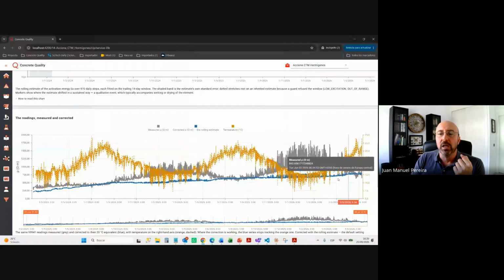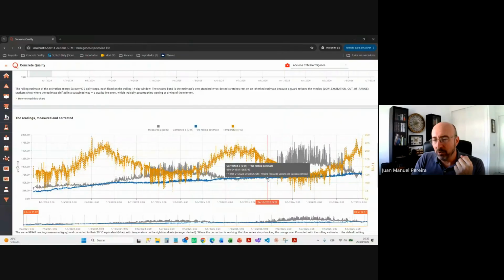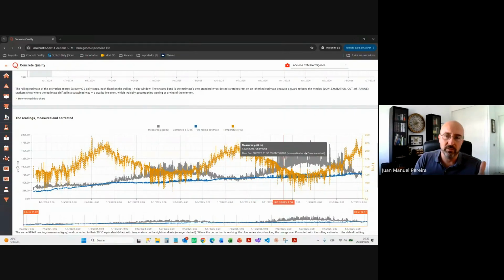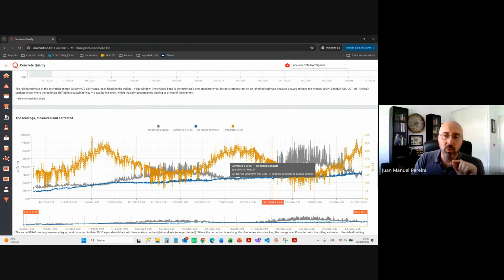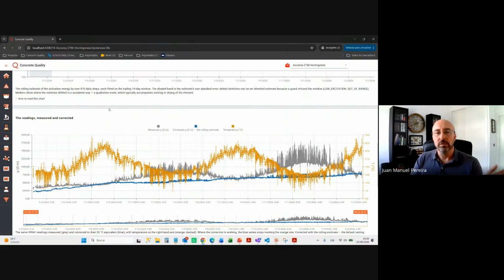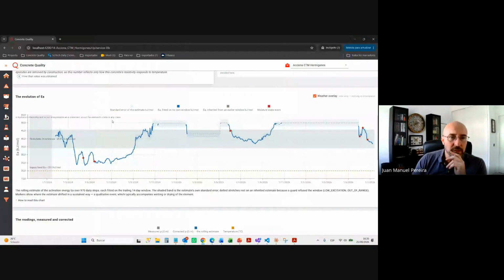This is important because it allows us to correlate a reading we have in a real structure to what we would be reading in a laboratory environment, because we correct it as if it was 20 degrees, as in a laboratory. So this will allow us later to use any type of test that you do in the lab, whether RCPT or chloride diffusion test, whether normal or accelerated, etc., to correlate that to what we measure with the resistivity. But let me go to that part.